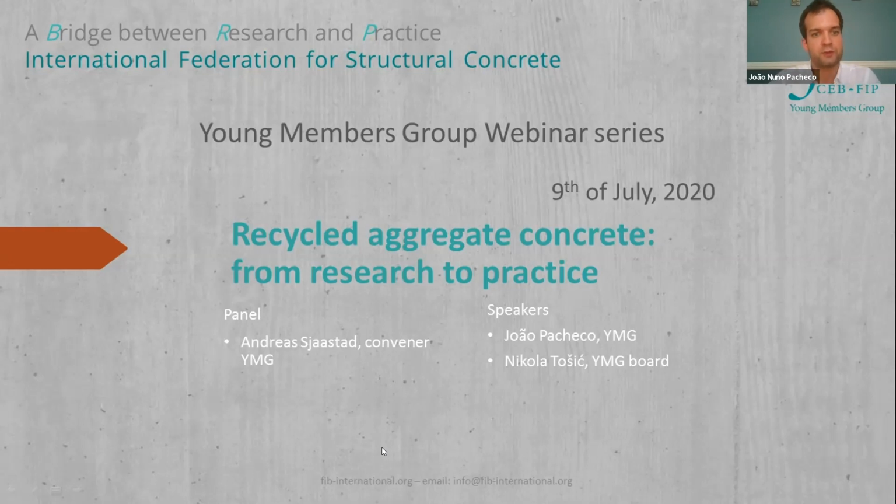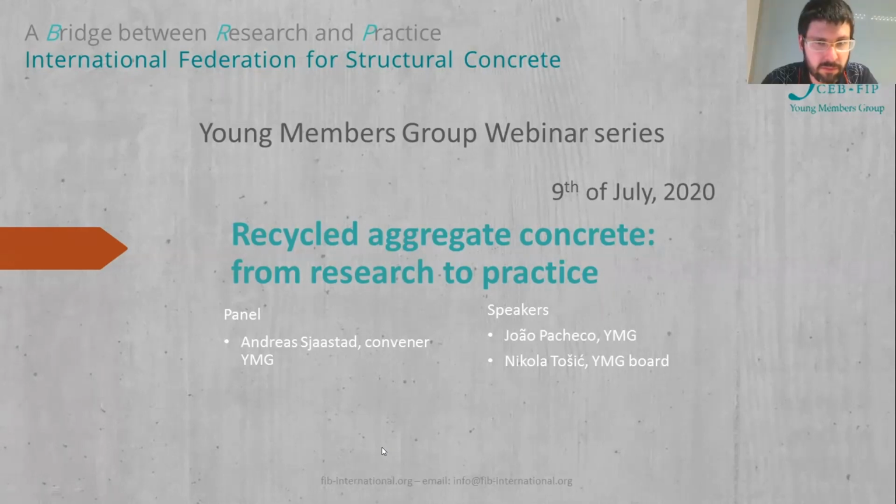Then Vlad has an interesting question about curing and compaction. Do you want to answer one and I'll answer the other? I told him the way I understood the question, but you can add. I just said that you can have challenges with workability if you're using saturated surface dry aggregates, and if not, you're adding water and so on. The thing to keep in mind is, in practice, you'll be transporting by mixer for, I don't know, half an hour, 1 hour. And you can have more significant slump loss than in natural aggregate concrete. So keep that in mind.